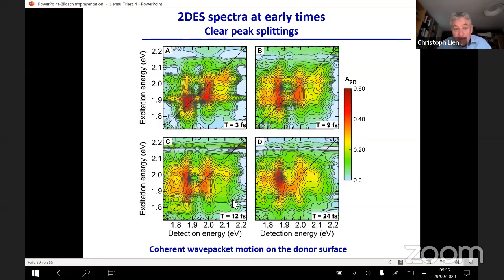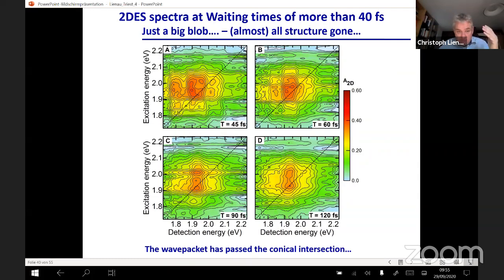This electron in its electronic state continues to oscillate on. That's what we see when we analyze these in a bit more detail. But then after 40 femtoseconds, it decides to completely change its character and to stop talking to the same vibrations. So obviously, the electronic nature of the excitation must have changed quite a bit. And as you will see, this is the signature of a wave packet that has just passed a conical intersection.